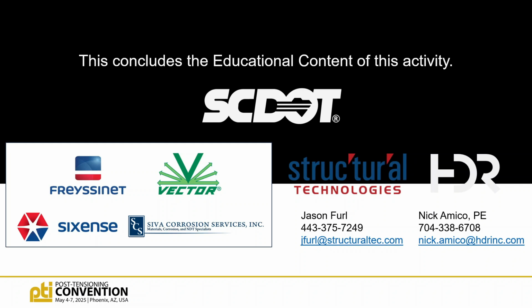So our two firms have talked about the capacitance testing and the magnetic flux leakage a good bit between each other. Can you just give me your impressions on that data and how you utilize that data? We did not find any significant findings with either system. So with MagFlux, we did find locations where there was some section loss, but as we investigated it further, more often than not it was local necking that happened during construction. You could find the necking on one wire. That's what we're seeing there. It did not find any significant issues that we weren't already aware of.